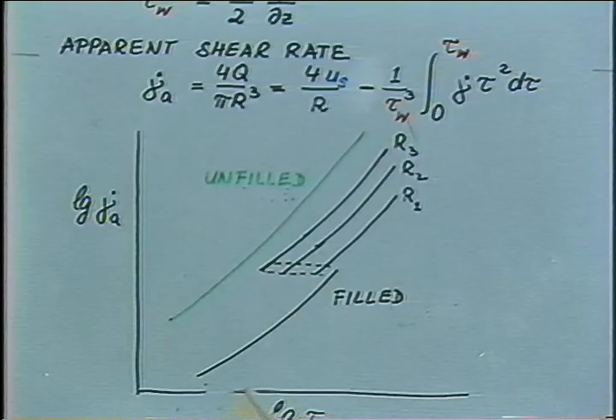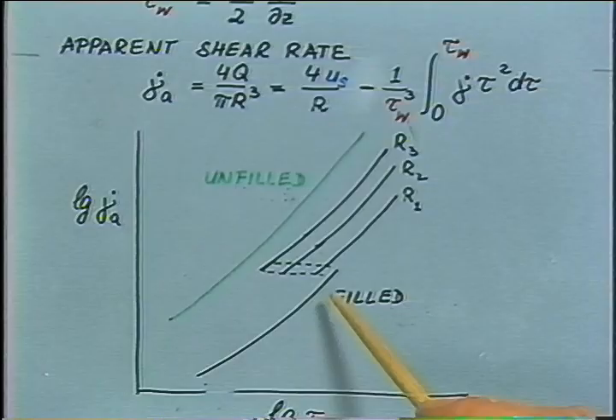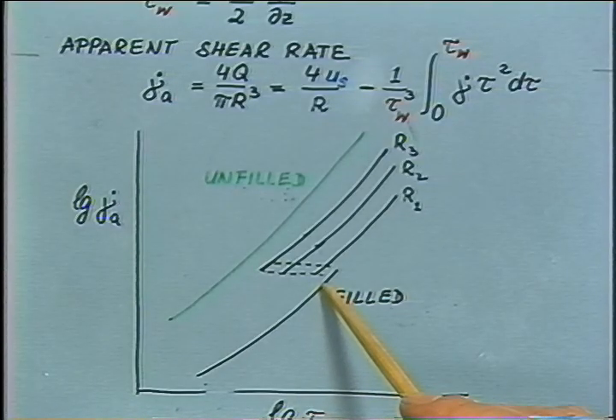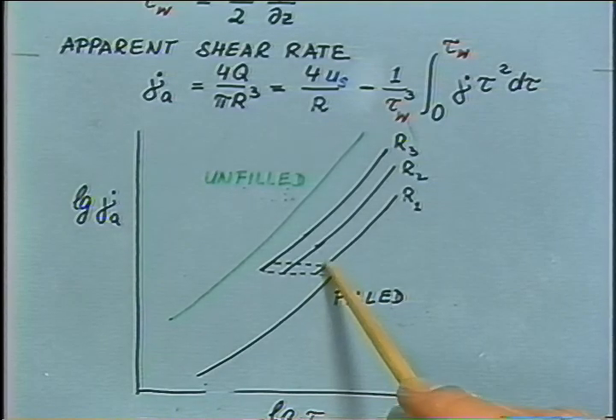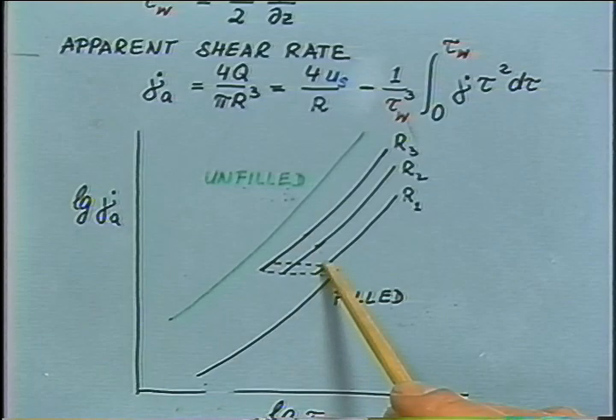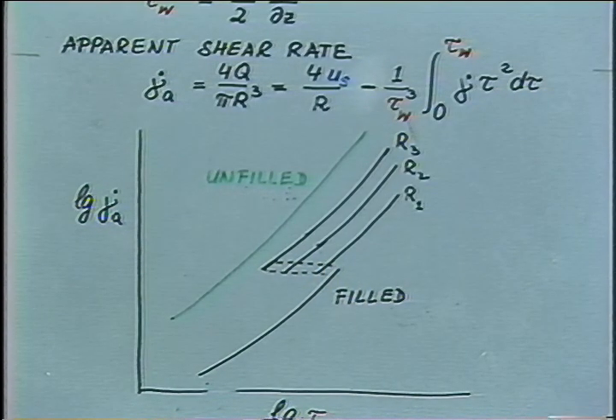Now, if we add filler, put substantial amounts of filler in that system, we still have the same type of behavior at low rates, but then when exceeding a certain critical value for the shear stress, the curves depend on the radius. There's some slipping occurring, and this contribution then is radius dependence, and we see immediately that the slipping is changing our experiment.